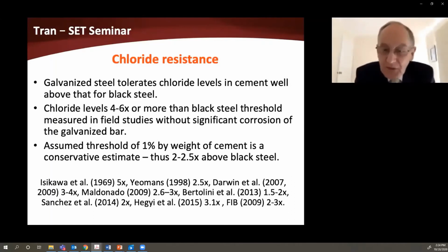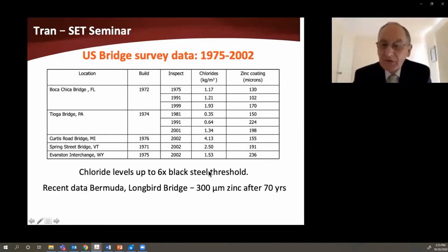Now, the reason we get these variations in this threshold is because of the nature of the zinc coating itself and also the nature of the environment to which they're exposed, the types of chlorides, whether they're embedded chlorides or whether they're chlorides that have ingressed from the atmosphere. But commercially now, and scientifically and technically, it is well assumed that the chloride level is about 2.5 times that of black steel.